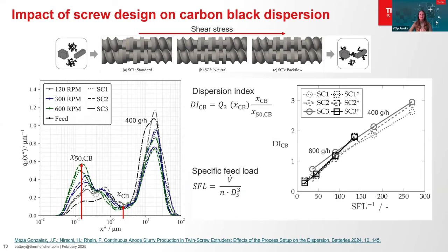Deagglomeration of carbon black is a significant challenge in the mixing of the electrode slurries. Through simulations of a digital twin and experience with 3 different kneading section designs, shown here on the top, 2 different throughput rates, and 4 screw speeds, a correlation was found between process parameters and the particle distribution of the anode paste. In the left graph, you see the particle size distribution in anode slurries mixed with the different screw designs and different screw speed. The dispersion index can be calculated from the median of the carbon black fraction from the size distribution. The higher it is, the smaller are the carbon black agglomerates.